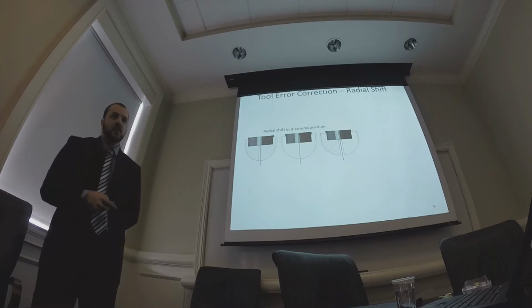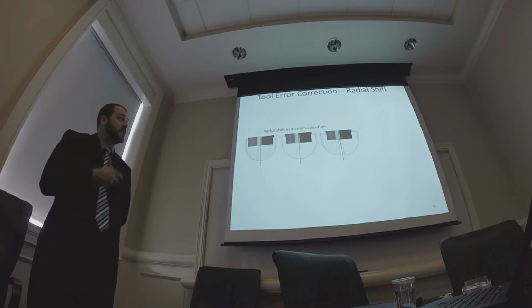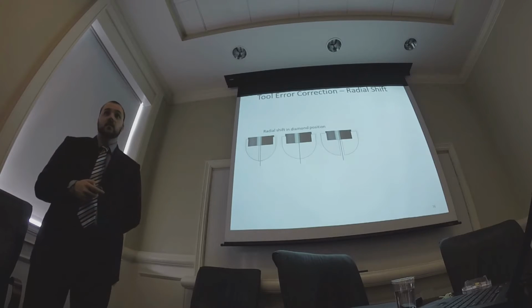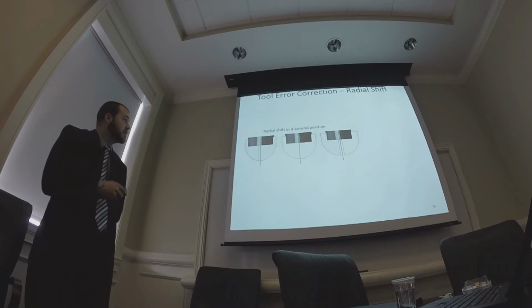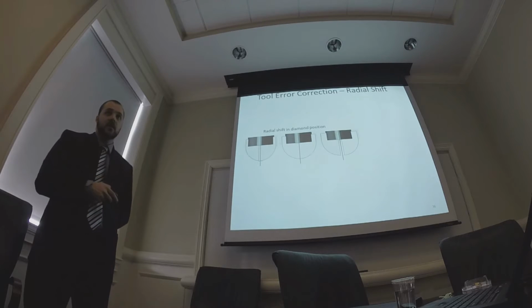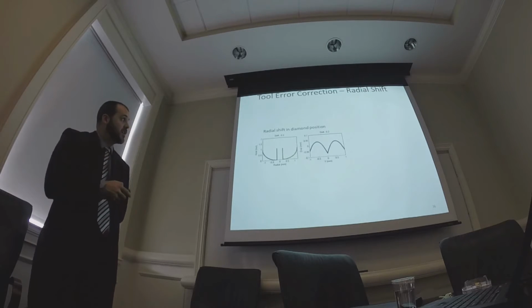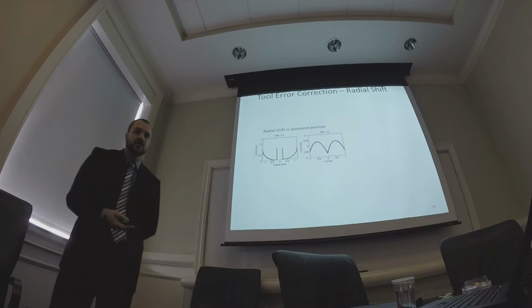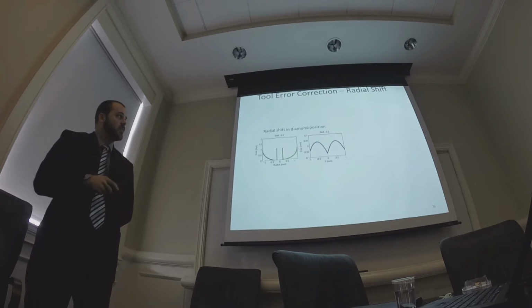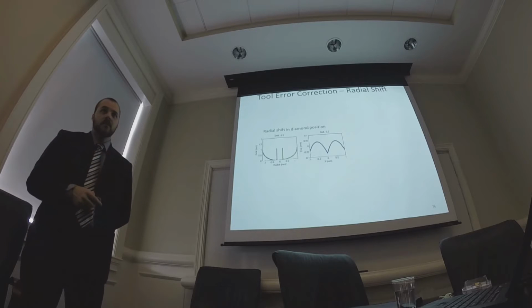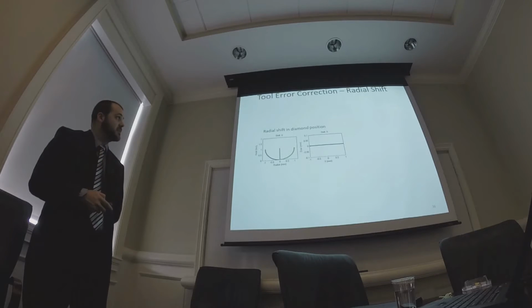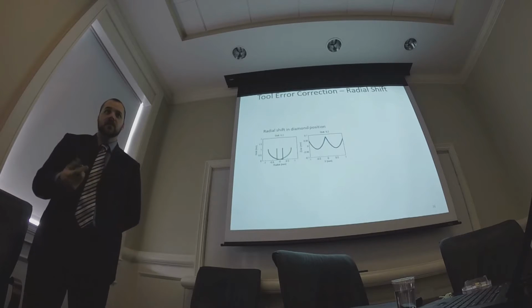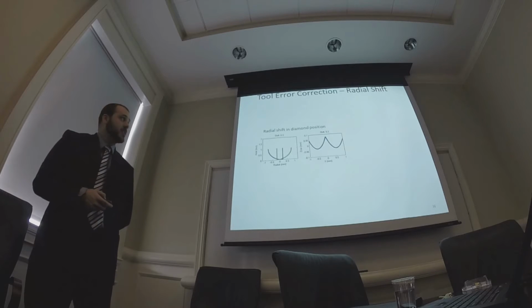So what does what I call a radial shift, a diamond position error, look like? What does it do to the surface? We could have the diamond too close to the middle where it needs to be, or too far out. If it's too far out, and we cut a concave sphere, we'll get what's referred to in industry as an M. If we sweep through past, we get no error. If we go the other way, we get what's called a W. So an M or a W - this is in the diamond turning instruction manual from the diamond turning company.